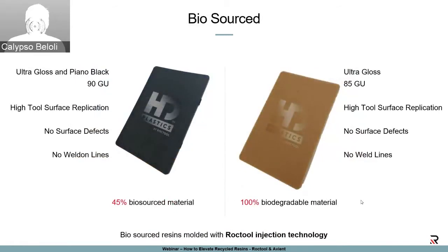Another kind of material is biosourced resins. So it exists now more and more, and that is very interesting. And the idea of Roctool is to evaluate how much we can improve and what we can do with this kind of resin. So on the left is 45% biosourced material. And as you can see, we have a really good replication of the texture, high gloss surface, and very interesting structure. So that means we are able to mold this kind of material.